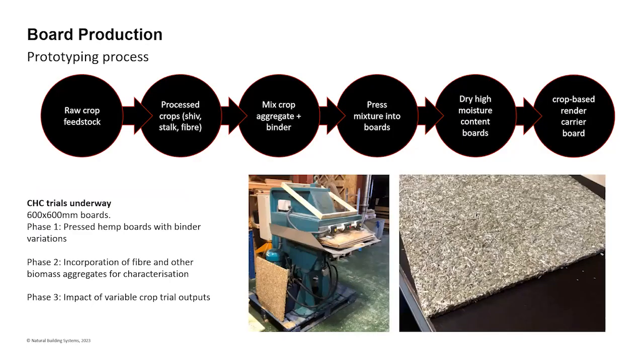We are currently starting trials. We're waiting for materials to come from the farms because the CHC project has only just started. And as new materials come, we're going to be trialing them, making boards out of them at different densities. So either the very low densities here, or this sort of density, which is a bit less dense than MDF or OSB, but has similar structural properties. And we can even go the whole hog and make something which is very robust indeed with the thermosetting binder.